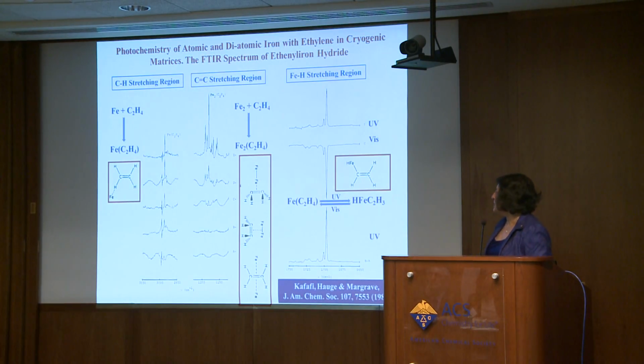The chemists in the audience will expect that the iron will actually interact with the pi system of the carbon-carbon double bond of ethylene, but here we saw the perturbation in the CH stretch of ethylene. This is a difference spectrum to subtract all the ethylene products. In this case, we look at the carbon-carbon stretch and we see perturbation on it, signaling that we have di-iron forming a pi complex with ethylene.